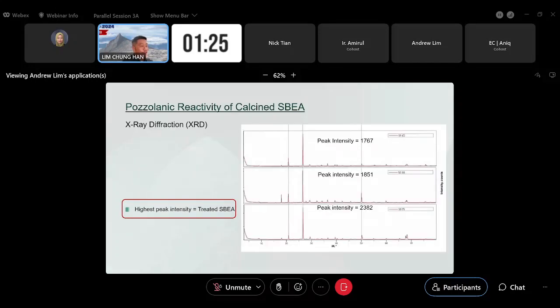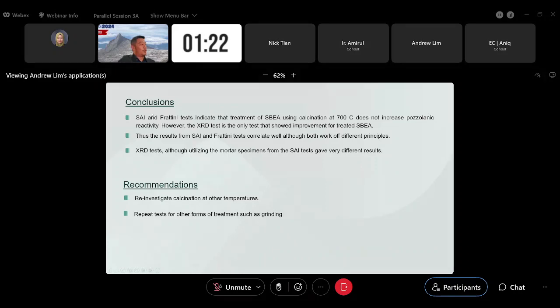So to conclude, what we're seeing here is the Fratini test and the SAI test, the first and the third test, are giving us very similar results. In other words, it's telling us that the treatment of the pozzolanic material is not actually giving us any benefit. However, the XRD test is telling us a slightly different story. It's telling us that the treated one is giving us better performance. So as you can see, between the three methods, there are some differences in the results you can get.